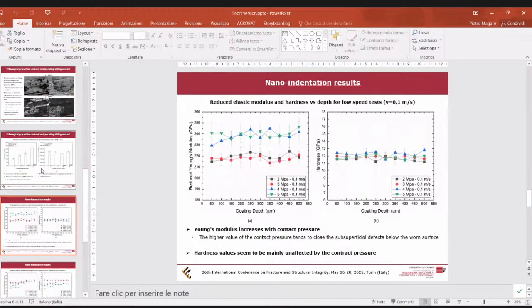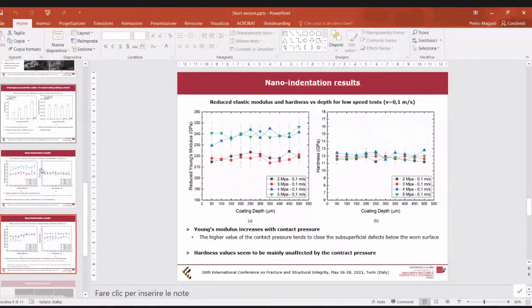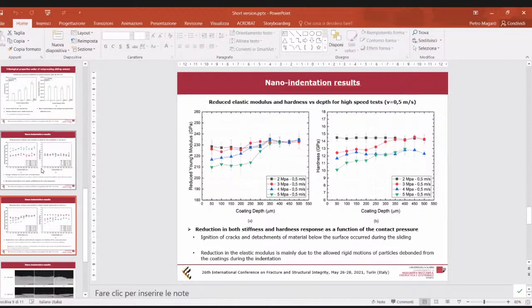Other activities regarded the evolution of the mechanical properties of the cross-section of the coatings measured by nano-indentation, in particular the reduced Young modulus and the nano hardness. You can see in this slide how the reduced Young modulus tends to increase with contact pressure in the case of low sliding speed, 0.1 meter per second. On the contrary, we can observe a marked reduction of both reduced Young modulus and nano hardness along the thickness of the coatings as a function of the contact pressure in the case of 0.5 meter per second.